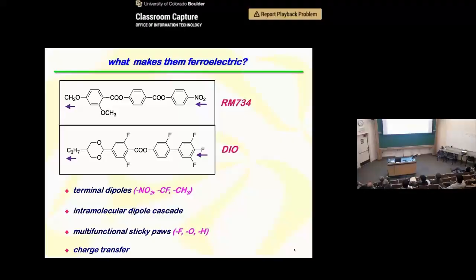The second commonality is that in the interior, there aren't contravailing dipoles in the interior of the molecule. So if you look at RM734, you basically have a charge density wave between the two ends. You have two dipoles and a charge density wave. The third feature are what we call sticky paws. So we have 3 Fs, each enabling a possible target for these dipole-dipole interactions.